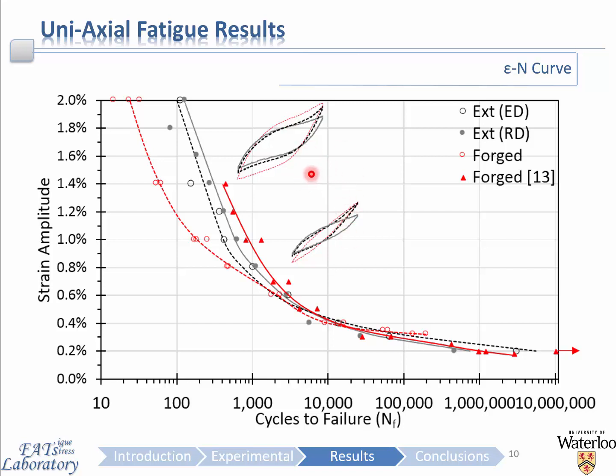This is due to the twinning in the compressive reversal, so this downward reversal, which causes a lower peak stress observed in compression. This is followed by detwinning in the first part of the tensile or upward reversal, which is then exhausted and followed by hard pyramidal slip, and this results in a higher peak stress that's observed in tension. The question is now, how does this asymmetric response affect the biaxial response of the material in fatigue?